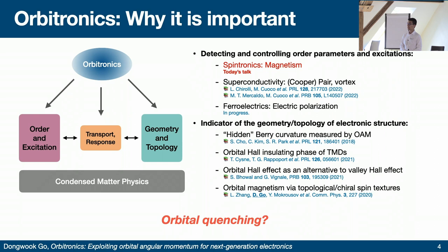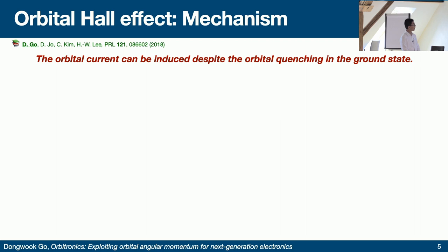Despite this importance, this field has been overlooked for a very long time. The main reason, as written in textbooks, is that orbital angular momentum or the orbital degree of freedom is quenched in crystals. Because of very strong crystal fields, orbital levels are usually split. That is why orbital magnetism is not so important for equilibrium magnetic moments — this is called orbital quenching.